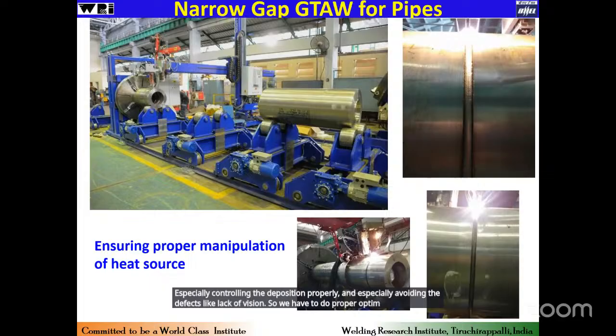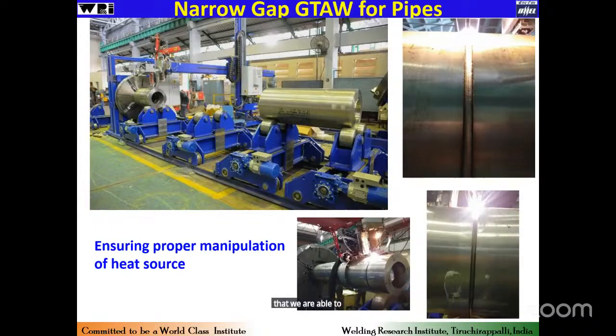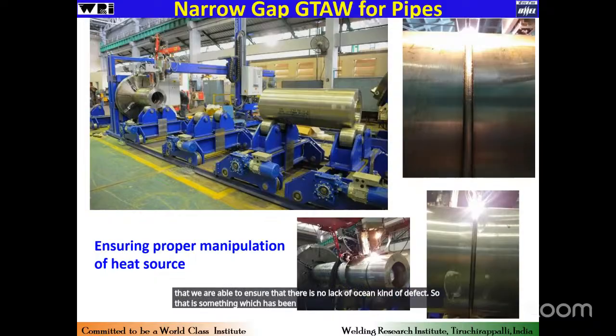The edge design or the joint design itself has been optimized accordingly to ensure we are able to achieve the penetration at the root from the top side, and we are able to manipulate and oscillate the electrode in a proper way, so that there is no lack of fusion kind of defect. So that is something which has been done. And you see on the right side the welded component.